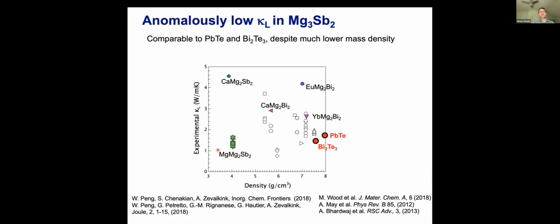And very strangely, when you replace the magnesium on the magnesium 1 site here with a heavier element, such as calcium, you actually get a big increase in thermal conductivity by a factor of 3, which is quite unusual. You would expect that heavier elements should lead to lower vibrational frequencies and thus lower group velocities and thermal conductivities, but that's opposite to what's observed.